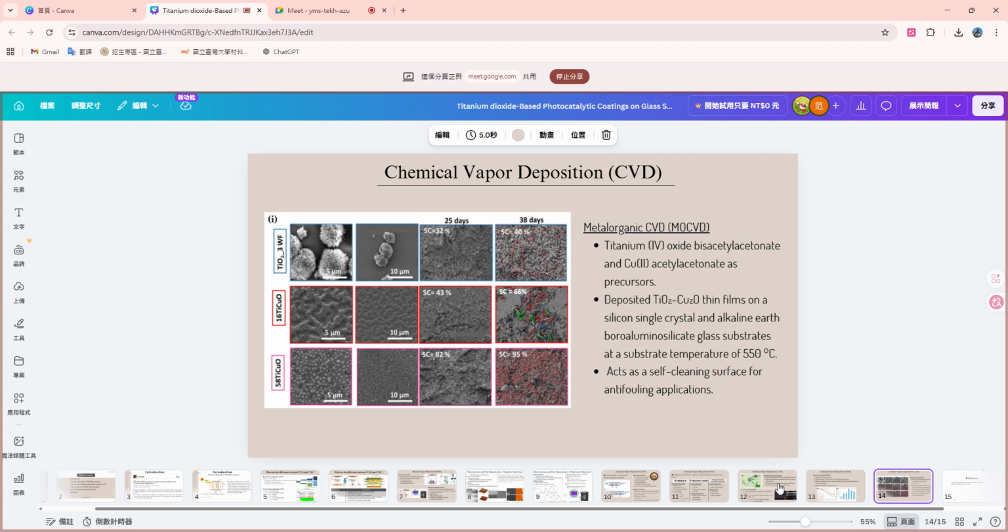Marine biofouling field test proved they had seawater resistant properties and showed a reduced colonization on TiO2 and TiCuO coating after 38 days. TiCuO composite coatings are promising non-toxic fouling release films for marine and industry applications.